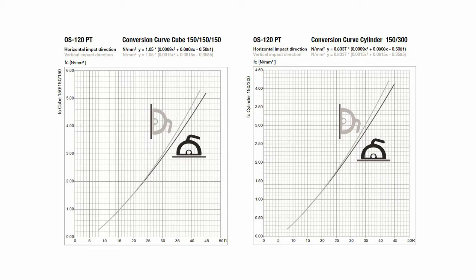And we can also see that the range of R values are much lower than the results I was receiving on my test block. That's because that was a fully cured test block. And in this case, we actually would be testing very low strength concrete, so possibly only just setting concrete.